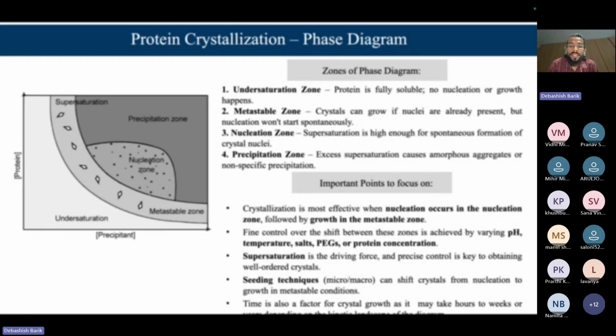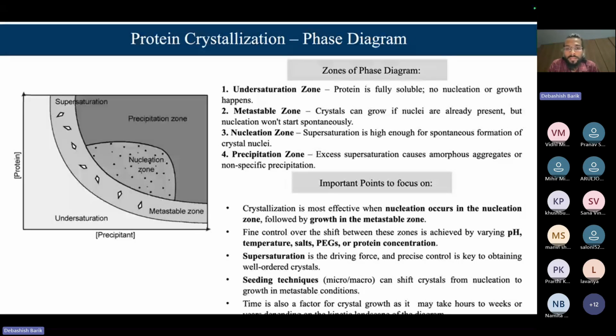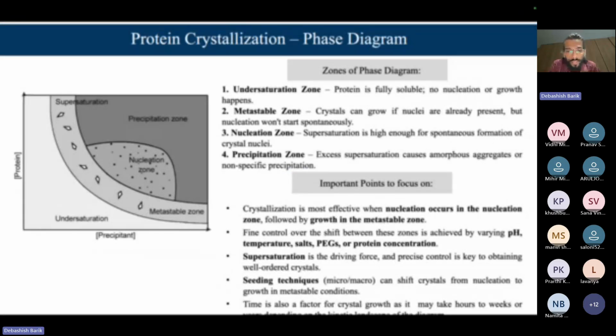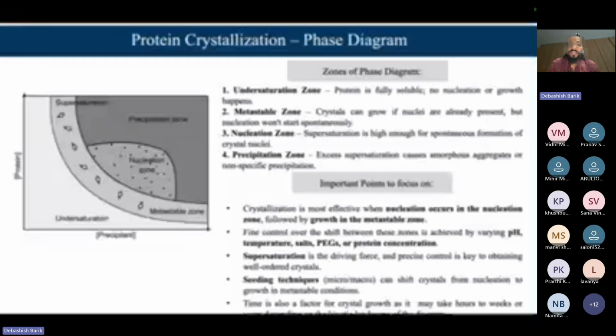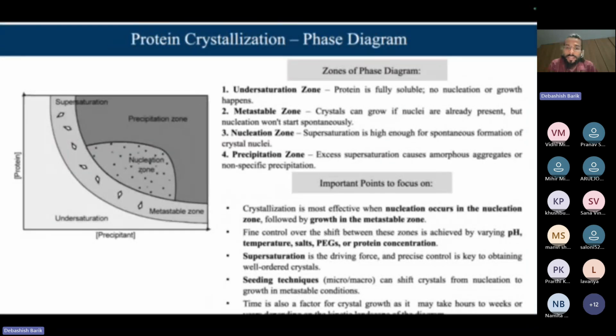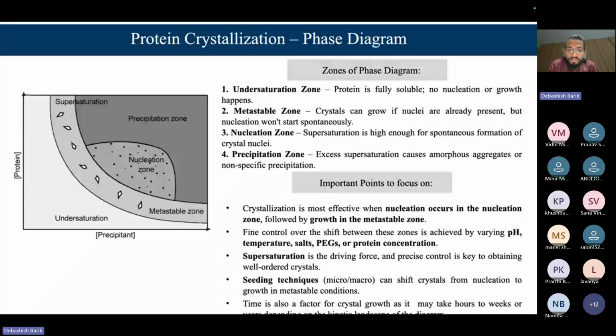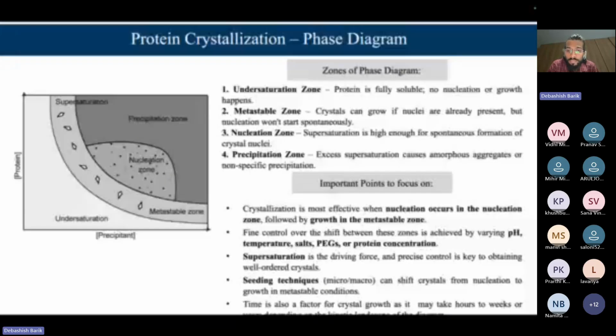Then there is the precipitation zone. If there is excess supersaturation, it can cause amorphous aggregates or non-specific precipitation, which will not help to get our crystals. So basically, crystals will not grow in this region. Then some important points to focus on. Crystallization is most effective when nucleation occurs in the nucleation zone, followed by growth in the metastable zone. Fine control over the shift between these zones is achieved by varying pH, temperature, salts, PEGs, and protein concentration. So we can shift these regions by playing around with pH, temperature, salt, precipitating agent, buffers, and protein concentration as well. The next is supersaturation, which is the driving force, and precise control is key for obtaining well-ordered crystals. Seeding techniques can shift crystals from nucleation to growth in metastable conditions.